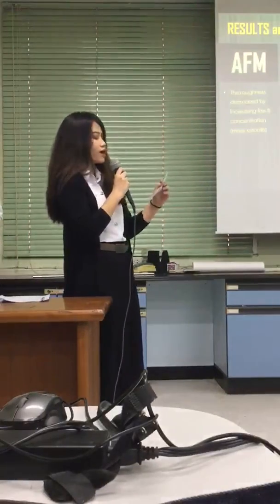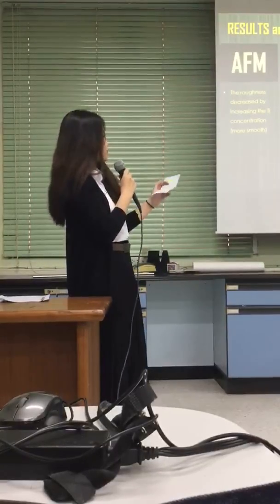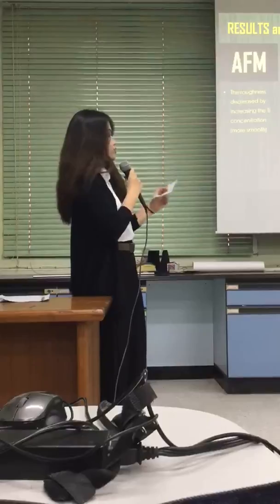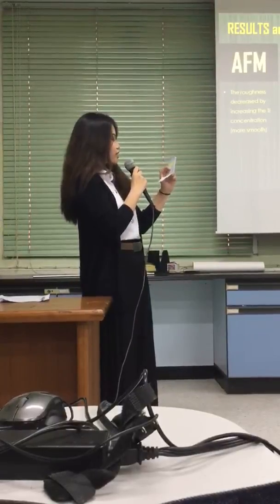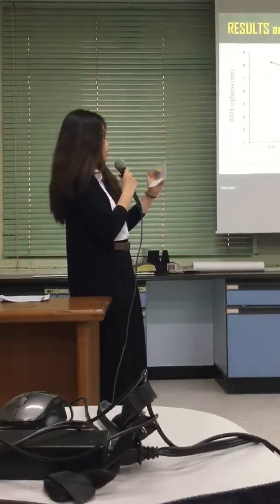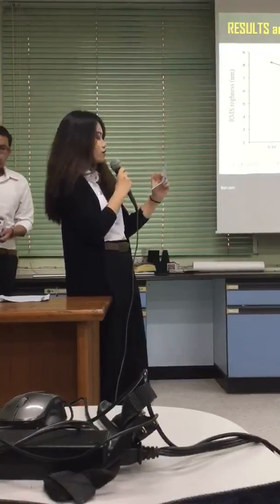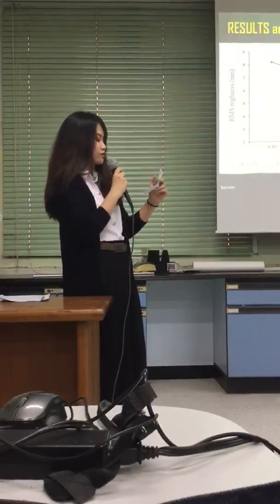Next, the roughness of samples is analyzed by AFM technique. In this 3D image, it shows that the surface becomes smoother as titanium concentration increases. In Figure 14, RMS roughness decreases from 8.2 nanometers to 3.4 nanometers upon titanium increase, due to grain size of sample decrease, which is in agreement with XRD result.